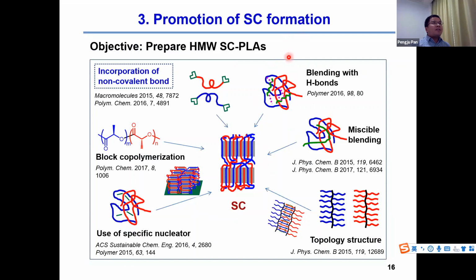Based on this consideration, we tried several methods to improve the stereocomplex crystallization of high molecular weight system. These methods include the use of specific nucleator, block copolymerization, incorporation of non-covalent bonding unit in the chain terminal, blending with hydrogen bonding component, miscible blending, control of topology structure. The fourth method was to improve the interaction between L and D chain.